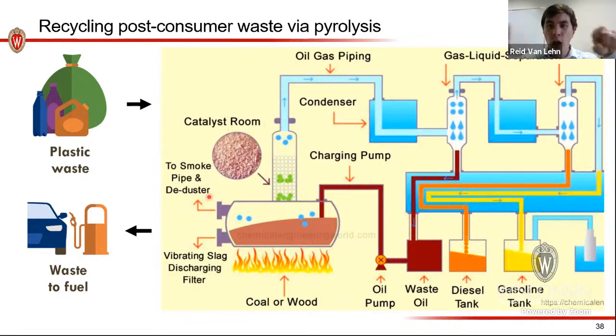So we're going to take our long chain we had from slide 1. At high temperatures, that chain will break into small fragments as small as the original monomer. This is not the same as incineration because we're not doing this in ambient atmosphere, but rather we're doing this in conditions where there's no oxygen, okay?